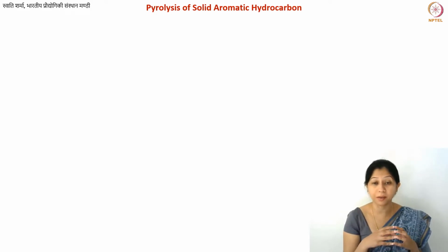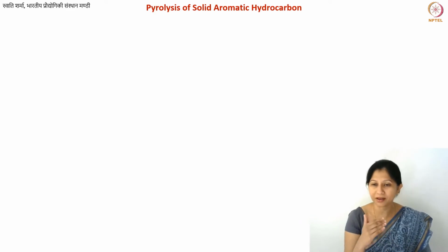For example, polyvinyl chloride can give you graphite or graphitizing carbon, or phenol-formaldehyde resins are going to give you glass-like carbon. So these kinds of pure polymers are well-defined polymers, and we also know the properties, or what to expect, in the carbon that comes out of these polymers. So let's talk about the mechanism of these.